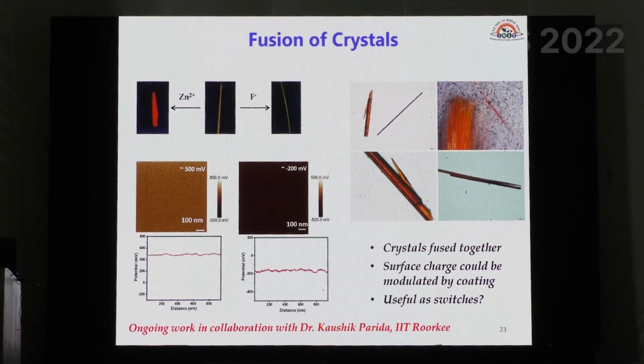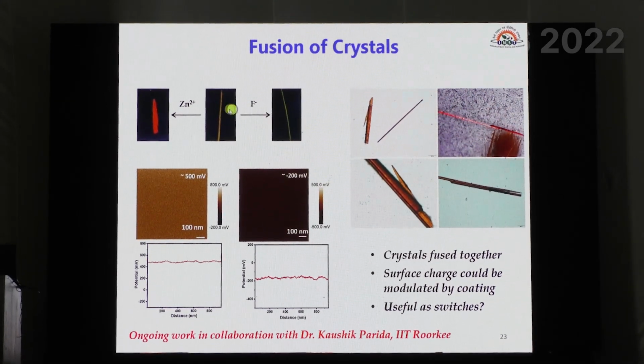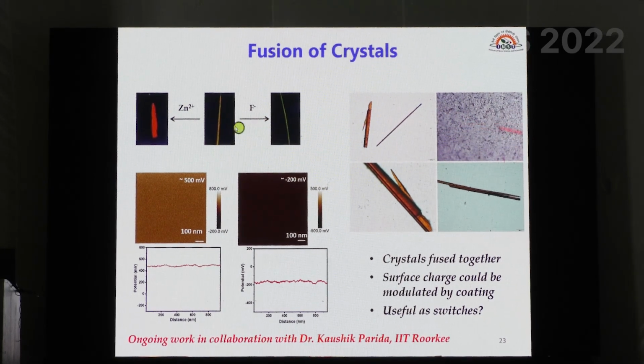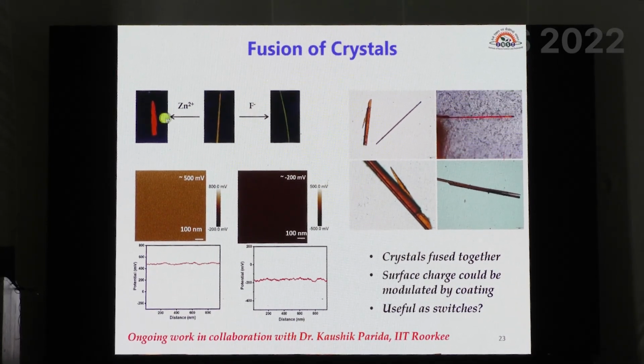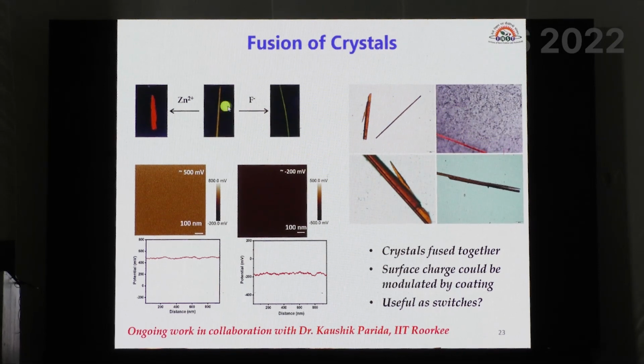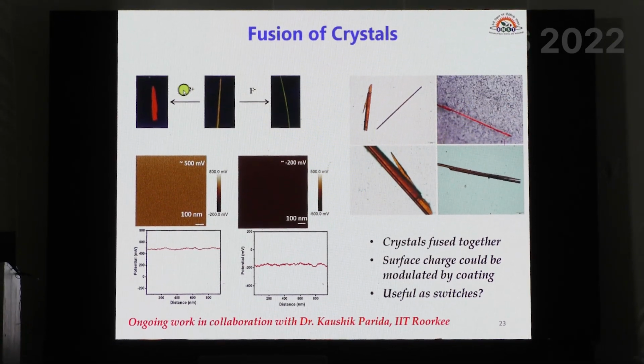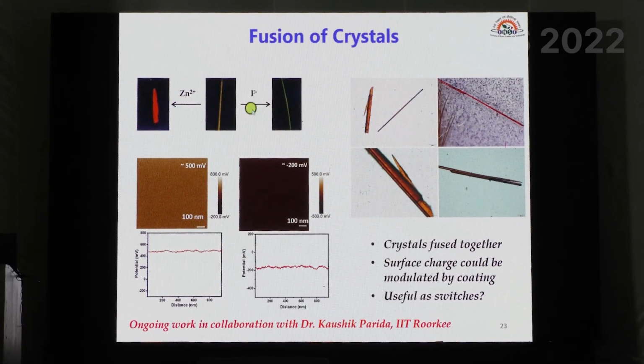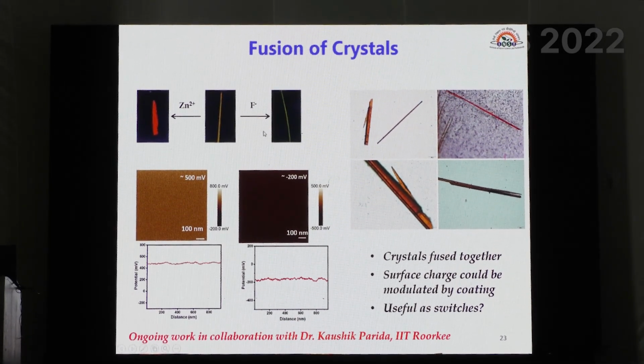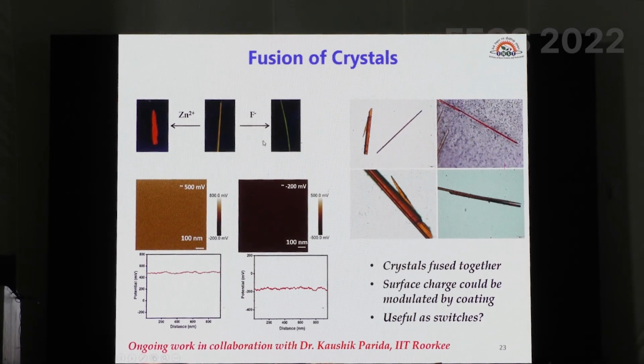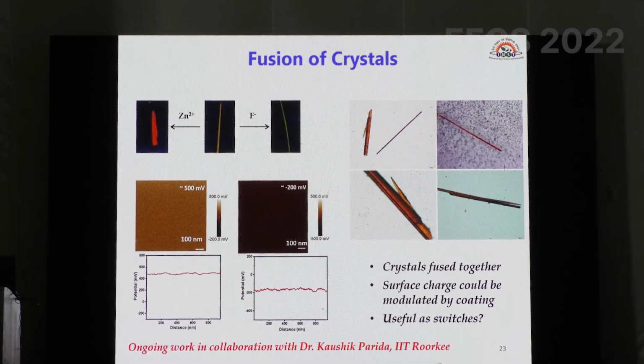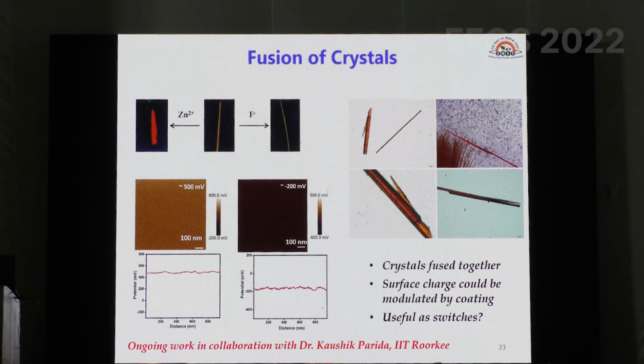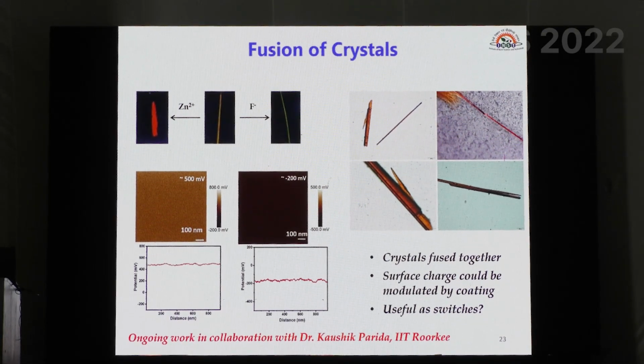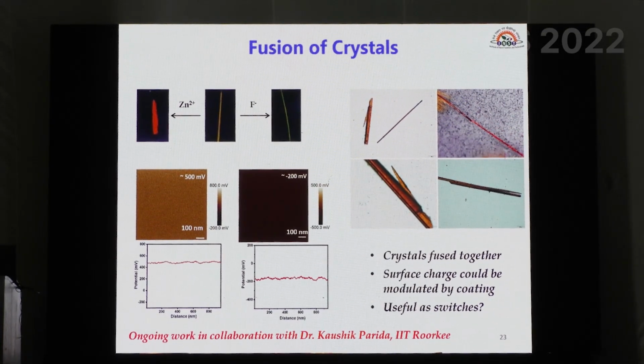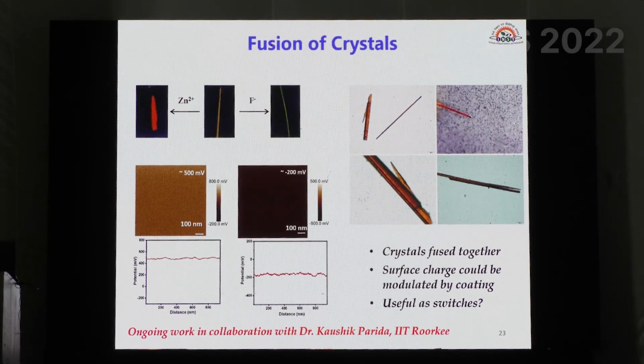As you can see here, this is a compound that we have synthesized, different from the other ones. This again binds to 2 different cations and anions, like zinc 2+ and fluoride anion. And when it binds, you can see that the color changes. That again depends on the binding of the material onto the surface of these compounds. So we end up with different materials. And the interesting part of these crystals is that we get different surface charges after binding of these metals.